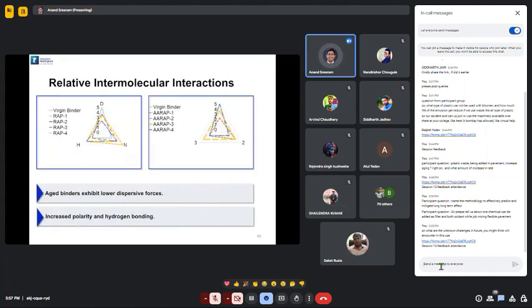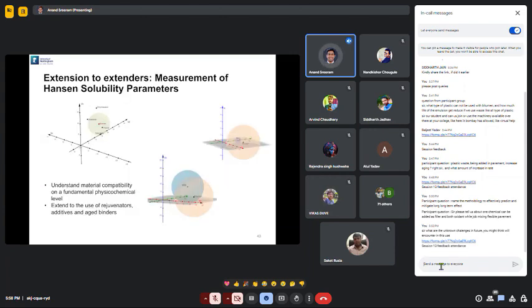We can also look at the extent of different kinds of intermolecular interactions, such as what happens when aging happens. So when aging happens, the polar forces inside bitumen become larger because you have more oxygen, right? Oxygen is a highly polar material, and we can quantify that semi-quantitatively when comparing different bitumen. So we could see that the aged binders have more polarity, perhaps more hydrogen bonding, and so forth. But I think the real beauty of